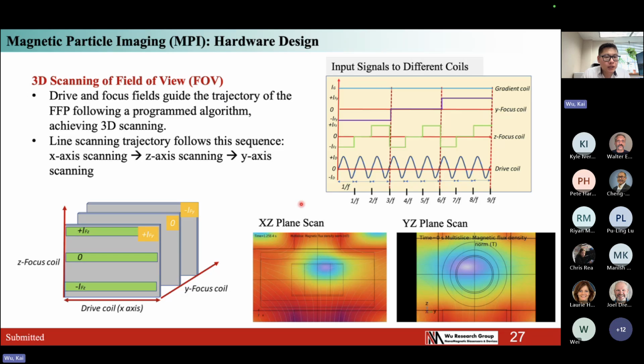Second, we do some modeling to see how to program the focus field to make sure that the field-free point can scan as we program it, following the trajectory we want. We did a very small modeling where we control the three dimensions, X, Y, Z. We have the drive field along the X direction, which can move the field-free point along the X direction. We also need the Y and Z focus fields to move the scanning trajectory from one line to the second line, the third line, then move to the other plane: plane 0, line 1, 2, 3, plane 1, then the minus plane, lines 1, 2, 3. This is just a demonstration of how the focus field programming can guide the trajectory of the field-free point to realize a programmed 3D imaging.